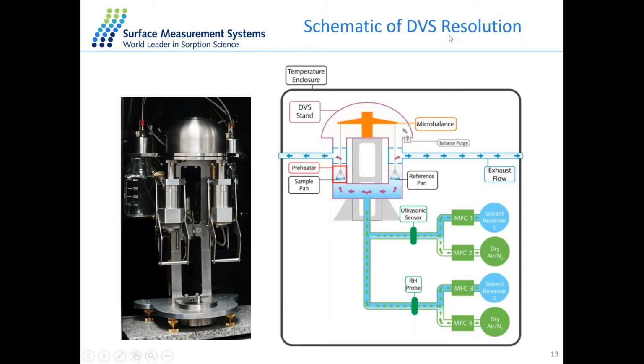This system can measure the sorption of water and organic vapor, as well as the competitive sorption of two different components. In the middle of the system here, we have the microbalance. It's connected to both the sample pan and the reference pan. We will put the sample in the sample pan and keep the reference pan empty. And as you can see, there are two bottles at the back of the system. One bottle is for water, the other bottle for the organic vapors.